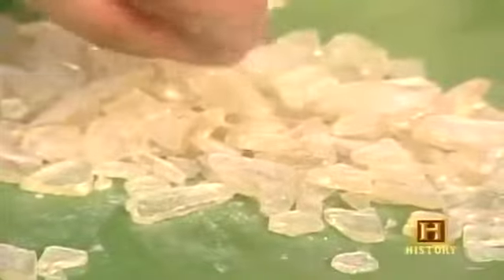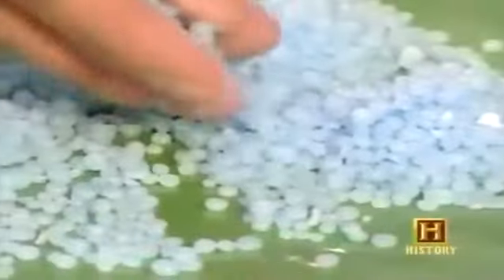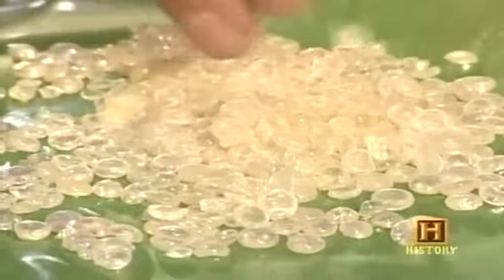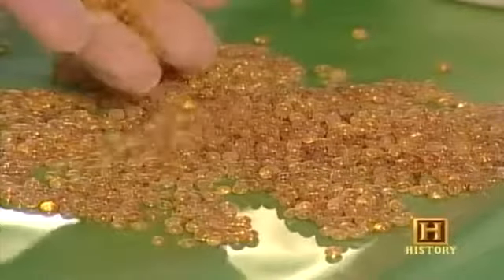These chemicals are weighed on the machine behind me to very precise weight tolerance. And just as an example, here you have an antioxidant which protects the tire from attack by oxidation. This is a resin. It helps it to adhere to the metal. This product is a wax that helps in the processing of the rubber and also helps the tire to stay black. This is another antioxidant. This product is an anti-ozonant, so same purpose except this time to shield the tire from attack by ozone. You would have anywhere from 3 to sometimes up to 8 of these different chemicals in a given formulation, but when you add it all together, it would only represent 3 or 4 total percent of the weight of the rubber compound.